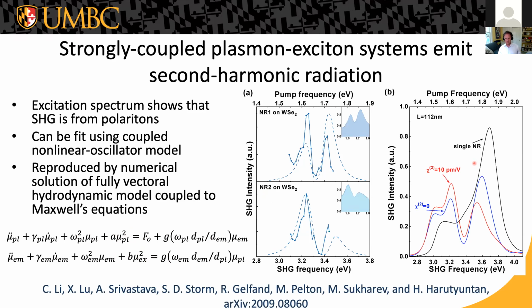And we get the same phenomena from more sophisticated calculations. So Maxim Sukharev, Arizona State University, did fully hydrodynamic models for the nonlinearities of the metal nanoparticles, and either incorporated chi-2 nonlinearity for the TMDs or not, and you could show the same spectra that we get experimentally in these fully numerical finite-difference time-domain simulations. So this is experimentally a first step in demonstrating the nonlinear optical properties of these coupled systems. There's maybe nothing terribly surprising going on here. The demonstration is that the polaritons are the nonlinear elements instead of the excitons.